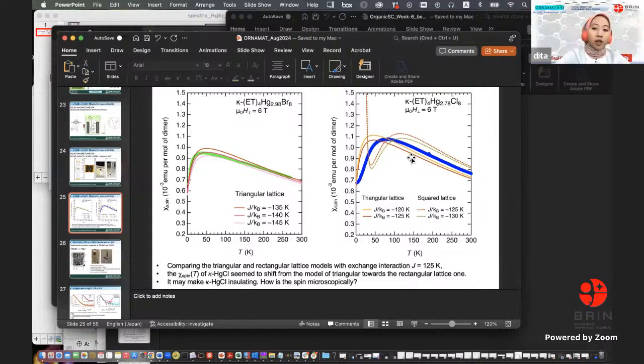But for the mercury compound, it doesn't fit with the triangular, right? But we also have the square lattice model. And for the square lattice model, when we set the exchange interaction to be 125 Kelvin, you see the solid line here, and then the dashed line here. So the data seems to be in between, around 125 Kelvin.